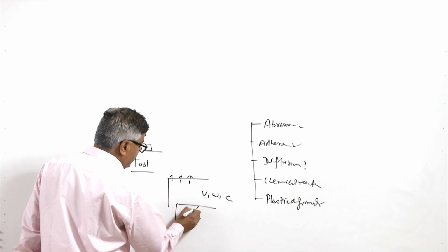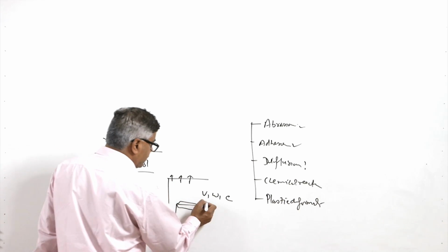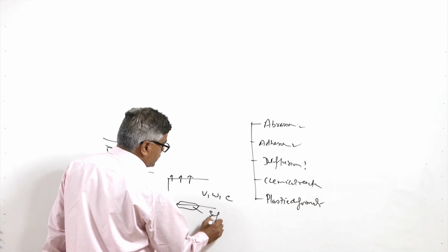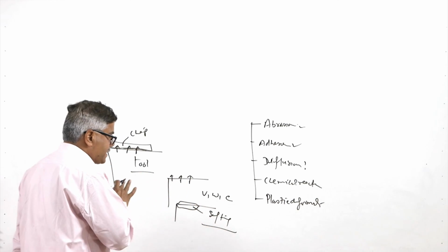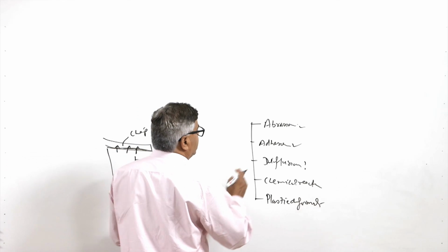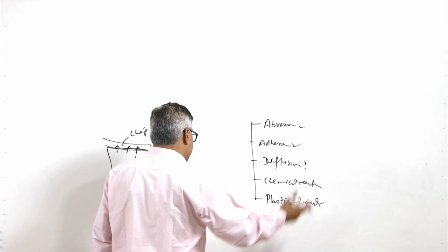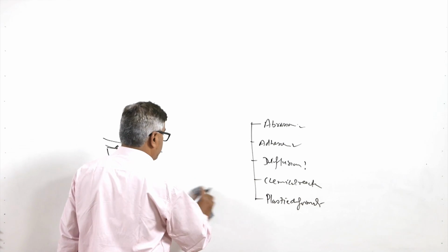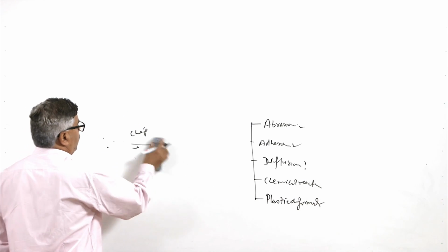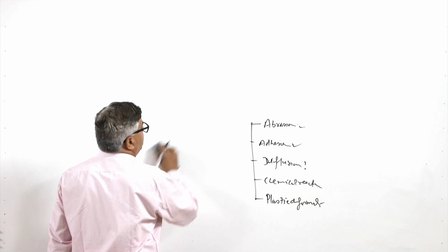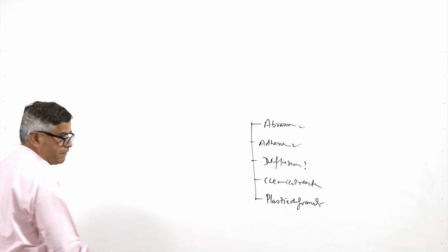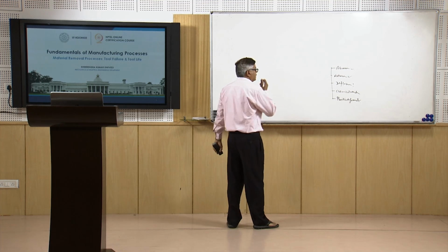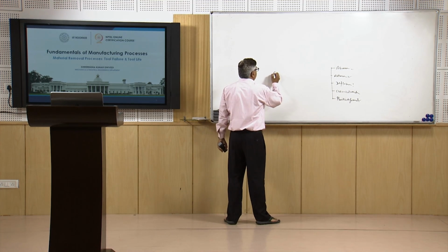This leads to depletion of certain alloying elements near the rake face of the tool, and the loss of alloying elements leads to softening of the rake face surface. This softening ultimately causes increased wear due to adhesion and abrasion. Therefore, the rise in temperature facilitates the diffusion of alloying elements from the rake face, leading to their depletion near the rake face, which in turn reduces the hardness and increases the wear by abrasion and adhesion.